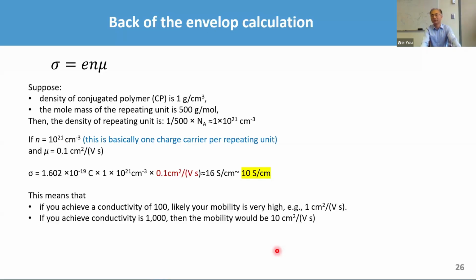That's a pretty low conductivity. It's still okay for the conductivity purpose, but it's still pretty low. But that's actually very high if you look at all these numbers. So if you're seeing someone achieving a conductivity of 100, and you understand that there is a ceiling on the carrier density, that means that the mobility of your material must be very high, like 1 centimeter squared per volt second. If you're seeing somebody achieve a conductivity of 1,000, then the mobility of that particular processed film would be 10 centimeters squared per volt second. That's really high mobility if you're working in the field.